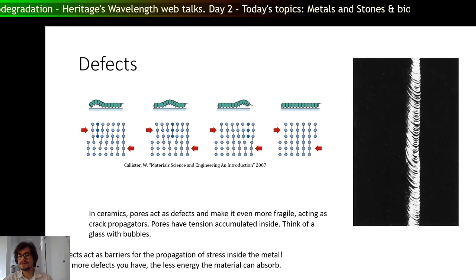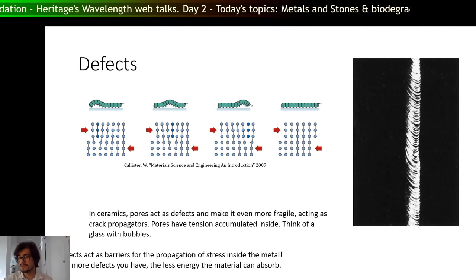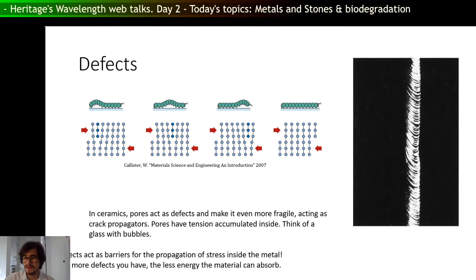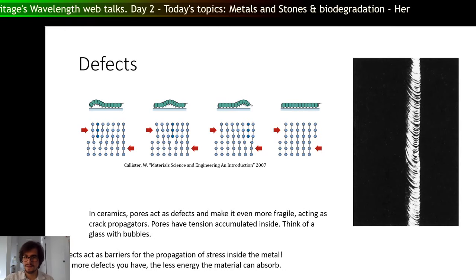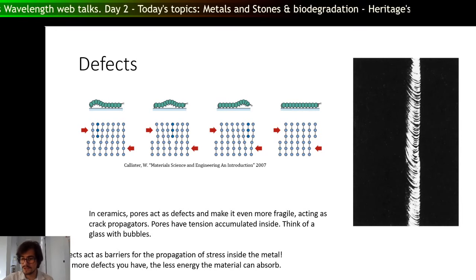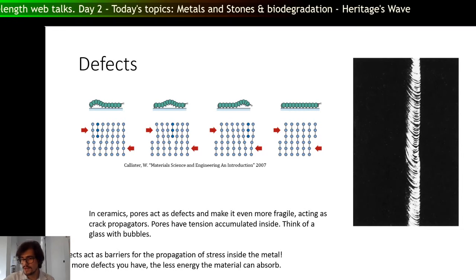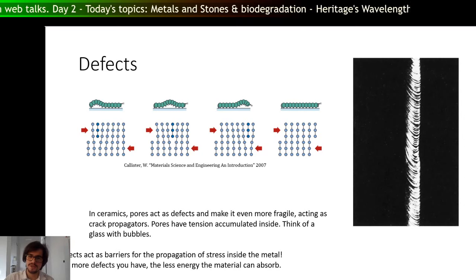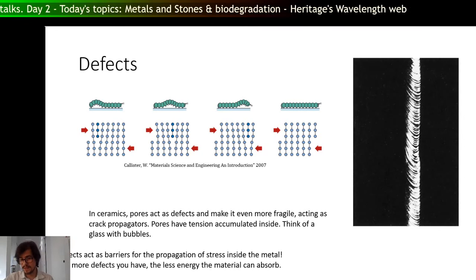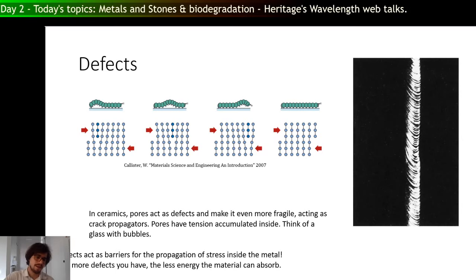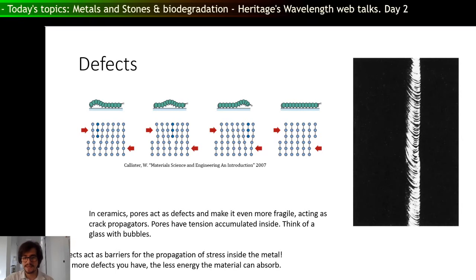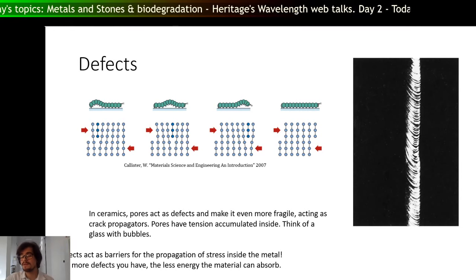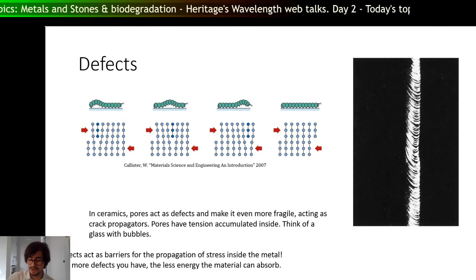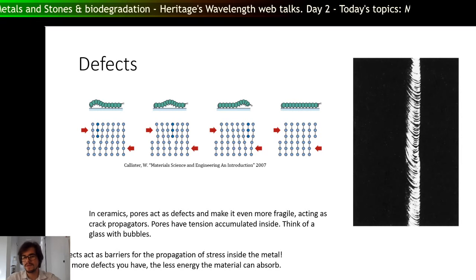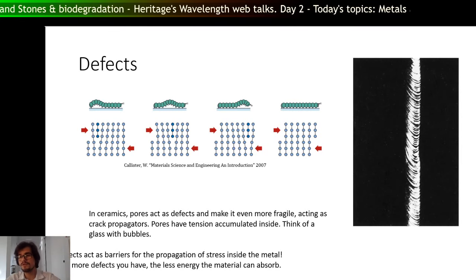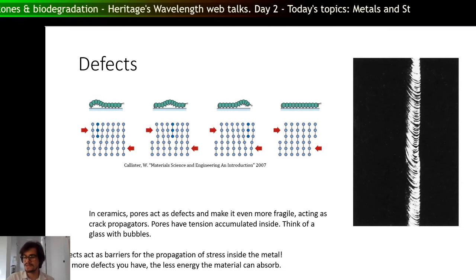In ceramics, pores act as defects, and the more porous your ceramic is, the more fragile it is, because it will restrain the propagation of stress. This will absorb energy, and pores act as concentrations of tension. So once that stress reaches the pore, it will just crack open, and the crack will propagate. Again, defects are barriers for the propagation of stress inside the metal. The more defects you have, the less energy the material can absorb, so it becomes more fragile. Then you have the transition from a ductile material, which we spoke of in the beginning, to a fragile material. So your metal will just break abruptly.